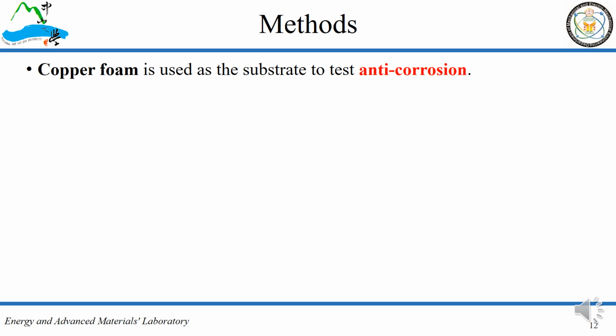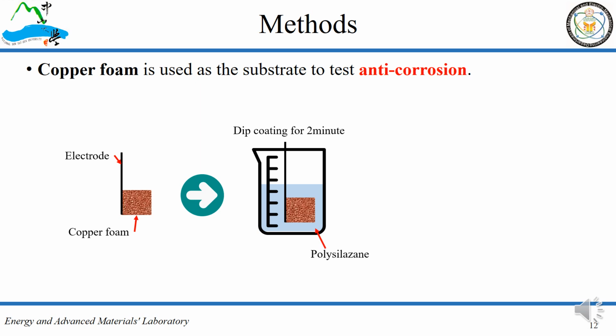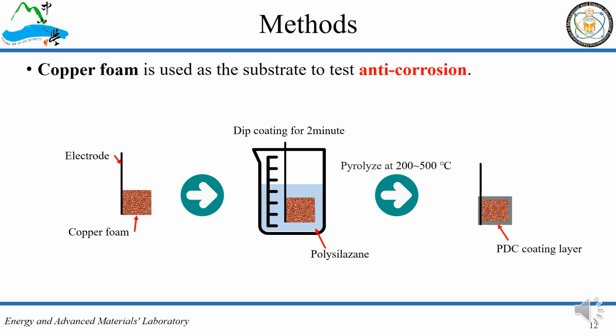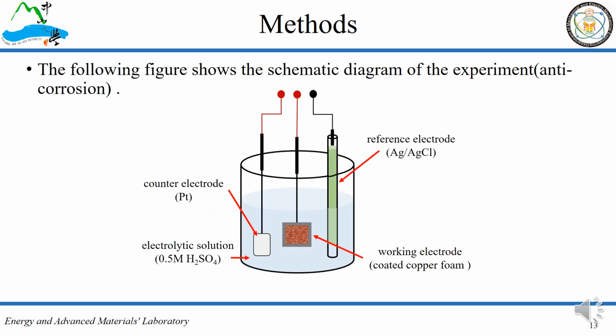Copper foam is used as the substrate to test anti-corrosion. We use a copper rod as the electrode to connect with the copper foam, and then dip coat it in the polysilazane for 2 minutes. Ultimately, the coated copper foam is pyrolyzed at 200 to 500 degrees Celsius to form a PDC coating layer. We used an electrochemical analyzer to analyze the corrosion resistance of the coating layer. The electrochemical analyzer consists of a working electrode, reference electrode, and counter electrode. The electrolytic solution is 0.5 M sulfuric acid.